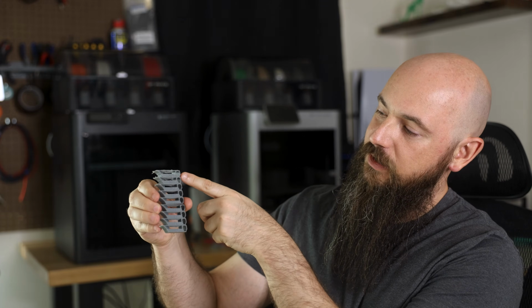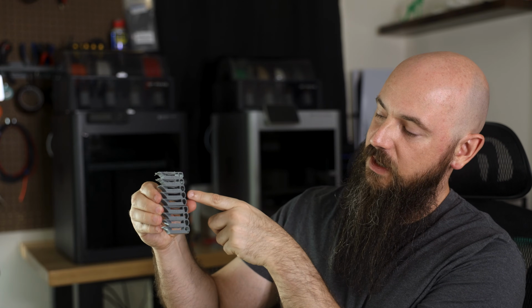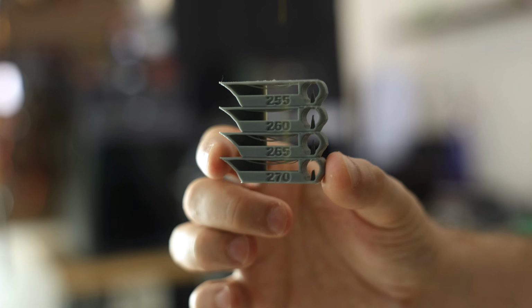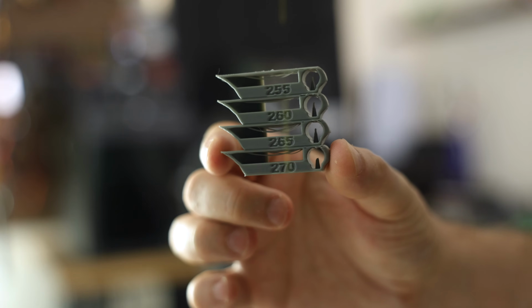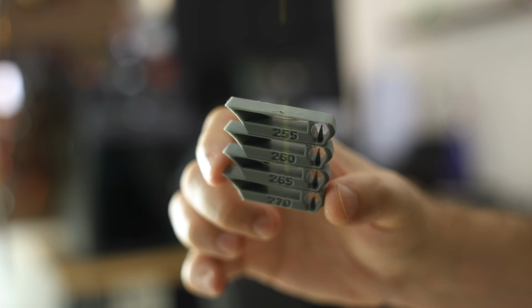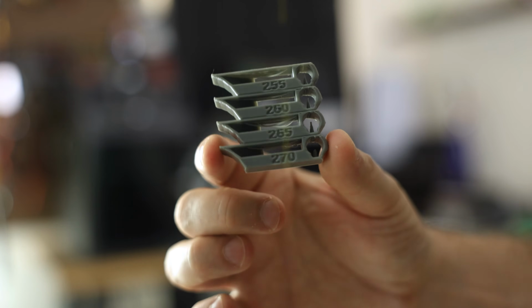As you go higher in temperature, you can see those features clear up, and around 250 seems to be the coldest you would go to clear up those issues. You can go all the way up to 270, and this brand of PETG actually says it should be printed from 215 to 230, which is interesting because at 230 it was not hot enough in my case. I've dried the filament in a filament dryer, and that didn't help. So I actually need to print this PETG at 250. So don't always follow the recommendations from the manufacturer.